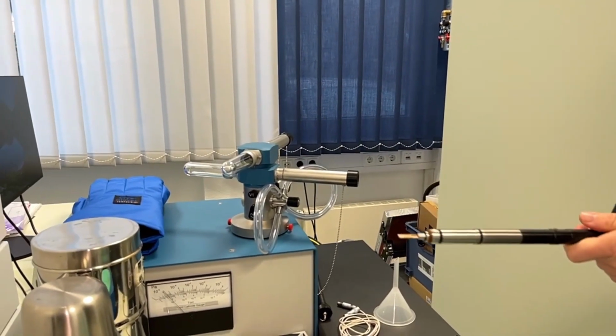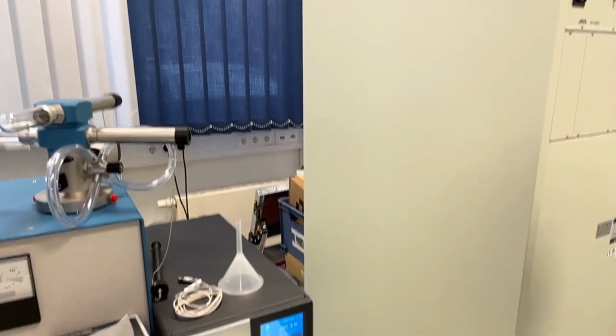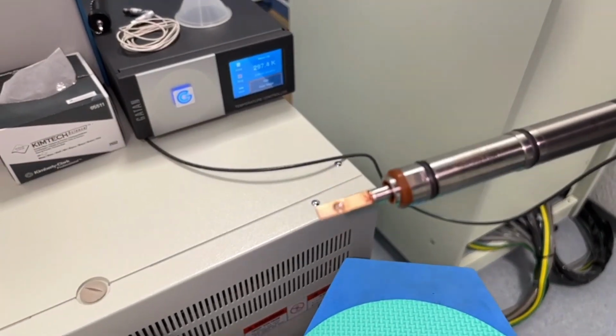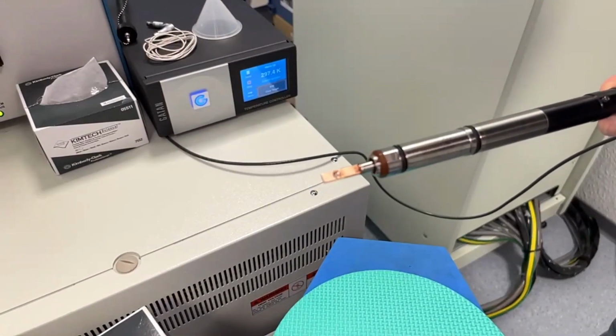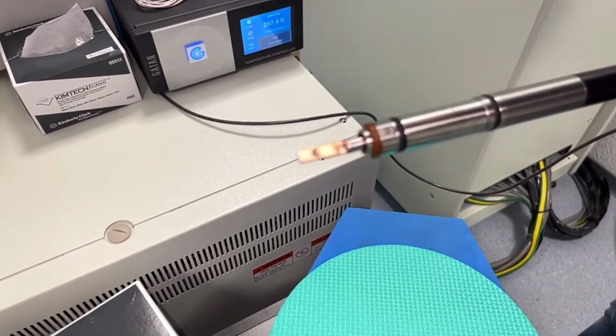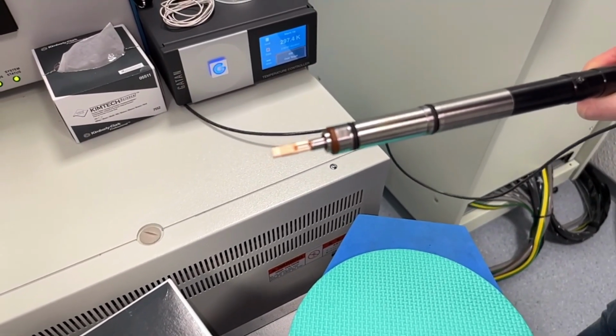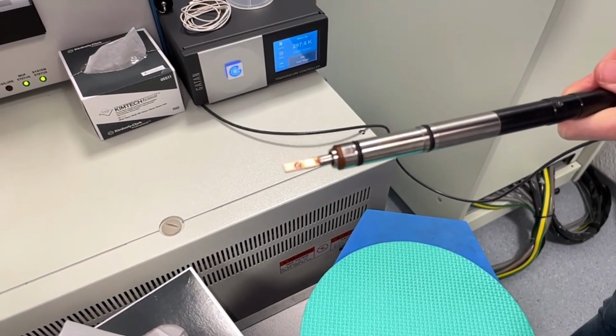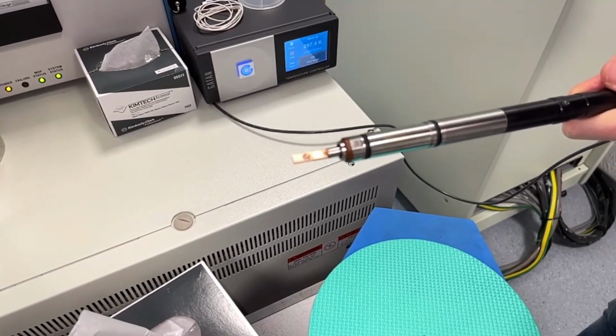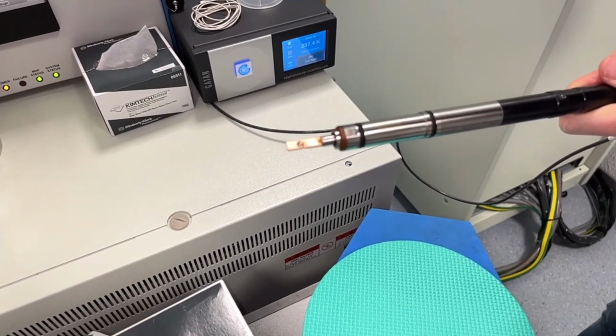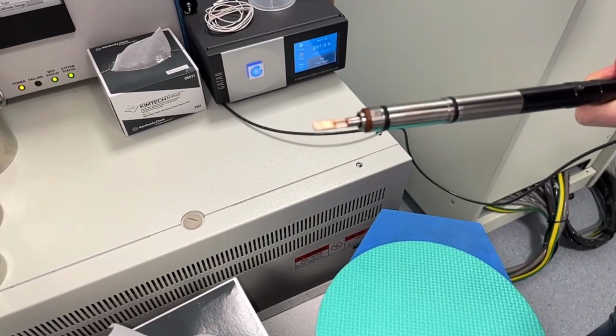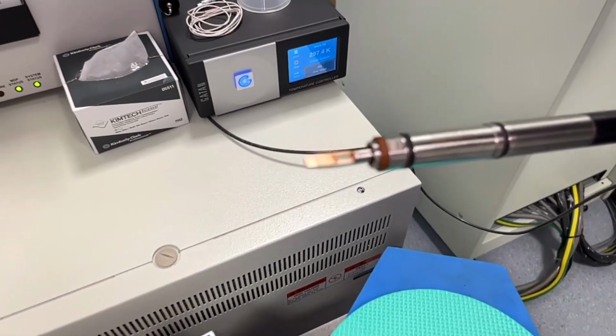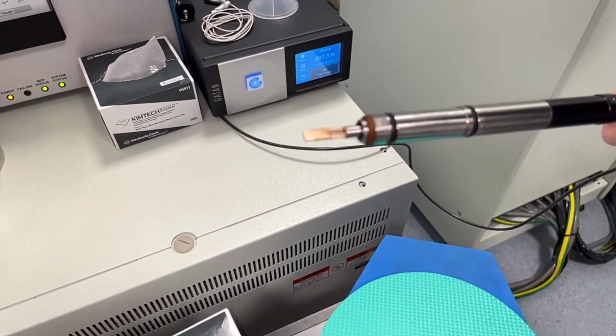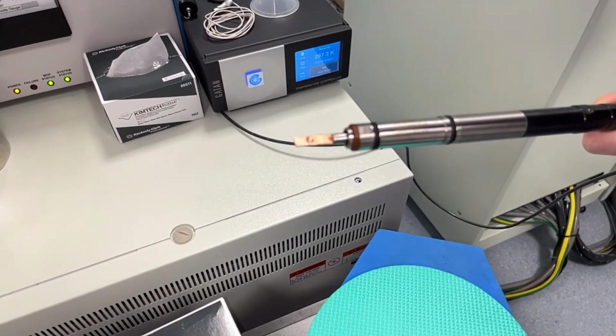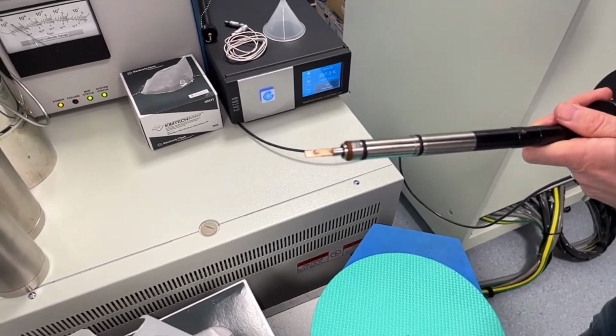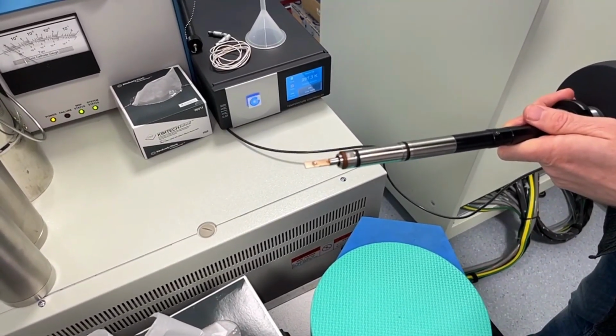And what you see at its tip is that it also contains a cradle where you would put your sample. There's even still one in, I see. And this can be covered through an actuator at the back of this holder. And this holder can be cooled down to liquid nitrogen temperature, and the sample can be cooled outside vacuum. And then you close this shutter and protect the sample from frosting once it goes again to ambient air, and insert it in this state into the vacuum of the diffractometer. Then you open it again, and you'll have a pristine cold sample that has not suffered from any icing or frosting while it was outside.